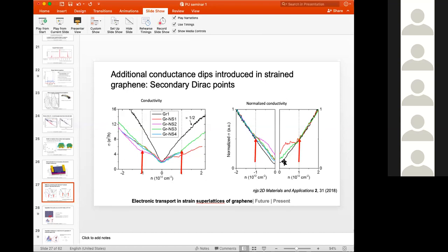But it is a fact that the data can be quite noisy, which is why right now what we're trying to do is encapsulate the graphene in hexagonal boron nitride. That will give us much cleaner resistance values, and will give us better curves, like we expect. Does that make it clear?